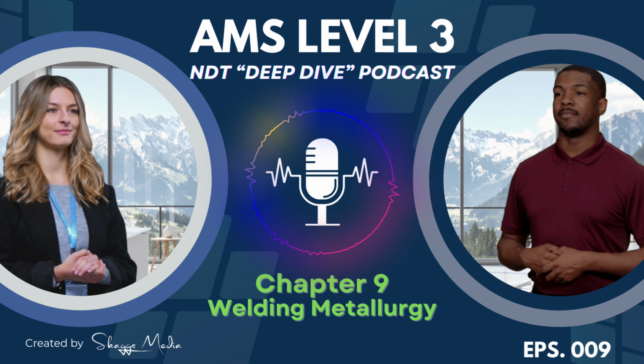So the inspector's playbook for preventing hydrogen cracking has 3 main parts. First, meticulous cleaning. Remove all moisture, rust, oil, paint from the weld area. Second, use low hydrogen consumables. These are electrodes, like an E7018, with flux coating specially designed to have very low moisture content, often requiring specific storage like heated ovens. And third, use preheat.